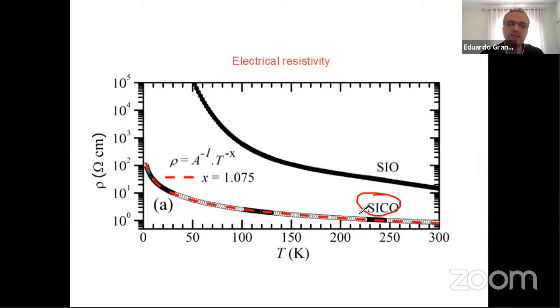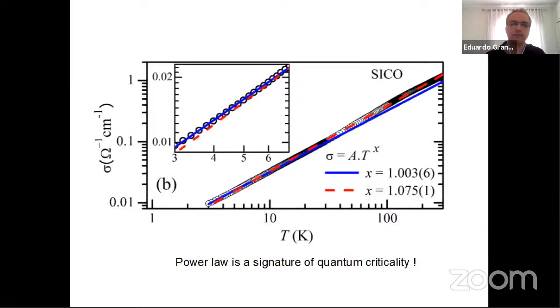We can fit this resistivity curve with a power law. So resistivity is a constant times temperature to the minus x, and this coefficient is close to unity. That's not the behavior that you expect for an insulating material. That's actually the behavior that you expect for a quantum phase transition. In a quantum phase transition, you have this power law behavior of the resistivity. If you plot the conductivity, which is the inverse of the resistivity, as a function of temperature on a log-log scale, that gives something very close to a straight line, which is again a signature of power law behavior.